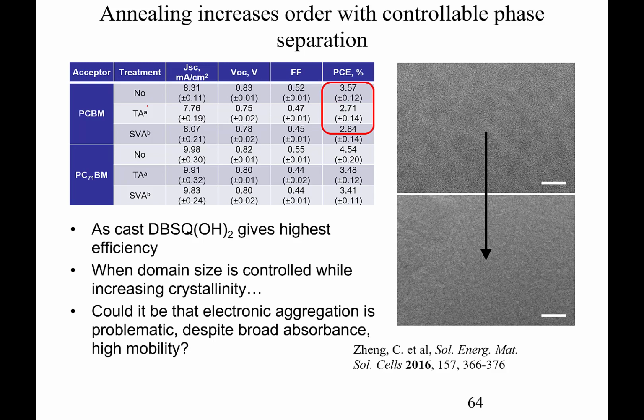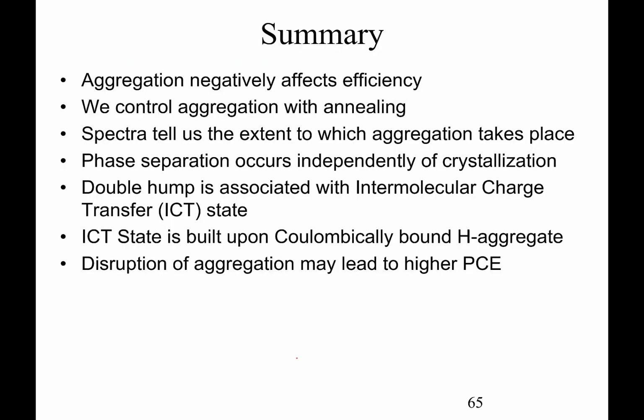We have questions about the importance of this aggregation. So we know that this aggregation is good for charge transfer. The charges can jump straight through, but is this aggregation the best for energy transfer? So let's take a quick summary view at the moment. We think that perhaps this aggregation negatively affects the efficiency. We've seen that in our devices. Nevertheless, we can control aggregation with annealing.